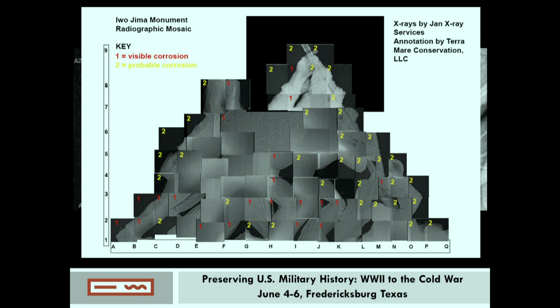This is just a mosaic that the guys put together for us so we could quantify to the Marines what exactly was going on. Areas marked number 1 on this slide were the worst condition. 2 were probable corrosion. We couldn't see because the X-ray wasn't good enough. It was a difficult thing to X-ray. There was an iridium source. More about that is in the paper. But they did a pretty good job, enough for us to get an idea what was going on. And all of these areas ended up being opened up. At first it was only a small group, and then we had to open all of them because they were all connected.